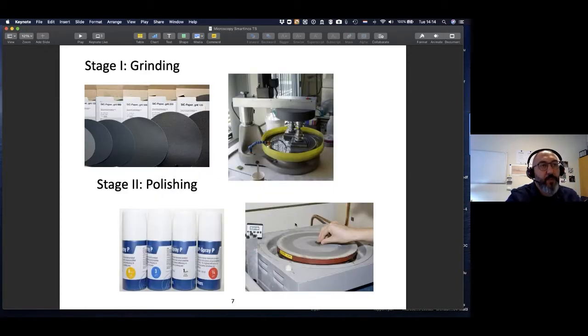Okay, and for that reason, for the first stage, you can use some silicon carbide papers, basically sandpaper, and then in the second part, you can continue with the diamond sprays and diamond pastes to further grind it all the way down to 1/4 micrometer, as you see.